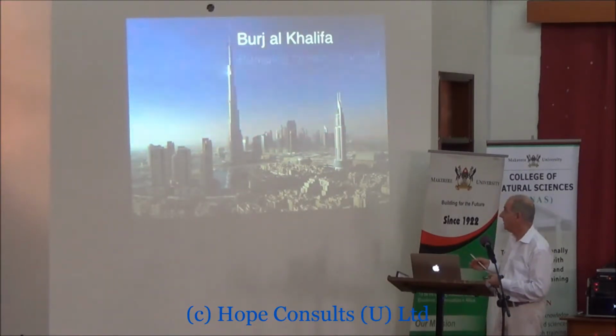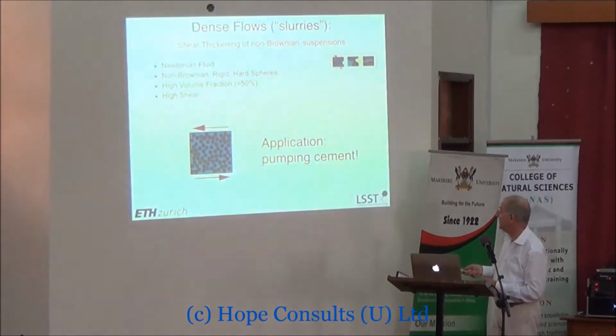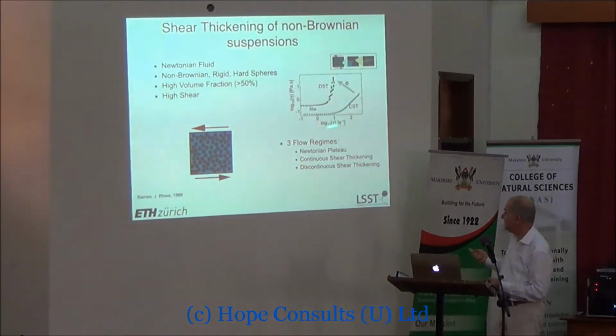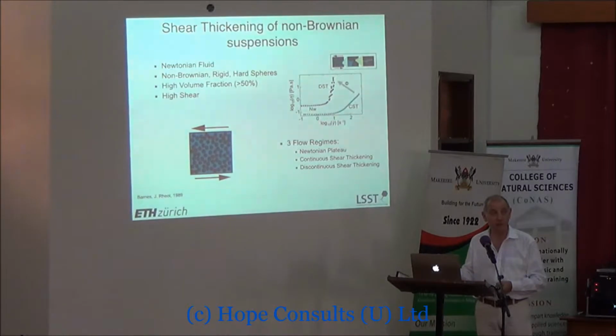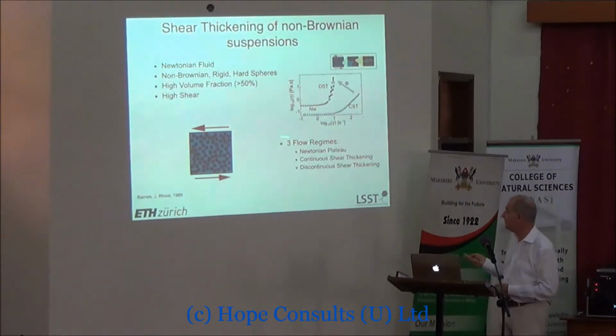And the rheology of it is a complicated business because what can happen is, this is the shear rate, so this is the speed, if you like, at which you're trying to pump the cement, and this is the viscosity on this axis, log scale. And as you go to higher and higher speeds of pumping, then you start to get what's called shear thickening, and you need more and more force or more energy being put into the pump to be able to pump that concrete. Now that's okay, it's predictable, and you can just turn up the current that's going to the pump. But that's called continuous shear thickening, and that's something that they have under control.